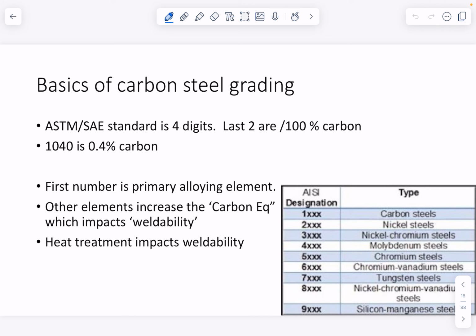I mentioned just a second ago 4140 or 4340. Those are these guys here, which are a molybdenum steel. If you're talking about springs, you're often talking about a 5160 type of steel. So knowing or having some idea what it is you're trying to weld will also help you understand what its weldability is like. And a lot of this comes down to what's called the carbon equivalent. If I'm looking at just a plain carbon steel, take a 1030 for example, I can pretty much weld straight onto that as long as I cool it nice and slow once I've finished. Don't put it in front of a fan or, heaven forbid, quench it.